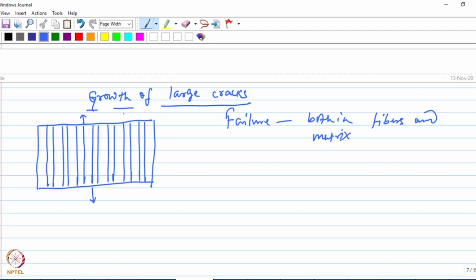So you have a crack in the fibers and you also have a matrix crack. Okay. The matrix crack propagates behind the fiber crack front. That means the matrix crack will follow this fiber crack, right? Yeah, so if this is the crack in the matrix and this is the crack in the fiber, this is how the matrix crack will be with respect to the crack in the fiber. Okay, so the propagation occurs in that manner. Okay, the matrix crack propagates behind the fiber crack front.